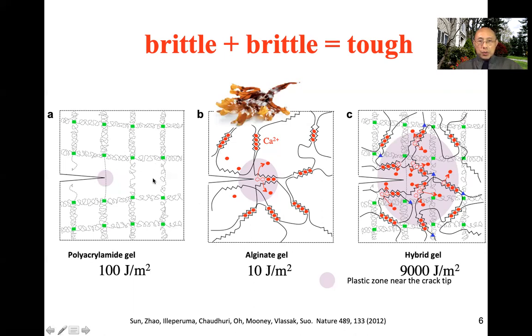When we mix these two things at a molecular scale, now when a crack comes along, before I break this polyacrylamide chain, the stress is already high enough to unzip many ionic crosslinks in the bulk. That's why toughness is high. So toughness needs to break the polyacrylamide chain, but also break many ionic bonds in the volume.